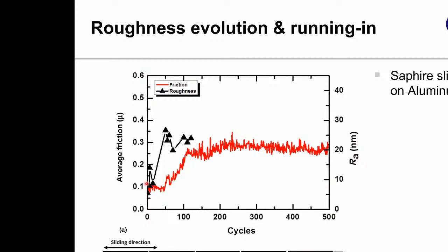Okay. So what this plot shows is experimental work, sapphire sliding on aluminum by Pancho Stoyanov, working with Martin Dienwiebel and Richard Kromick. The y-axis shows the friction coefficient, and the black curve shows the surface roughness measured in situ during this experiment. What you see in this case is some sort of running in, a bit untypical since the friction coefficient actually goes up, but at the same time the surface roughness goes up. There are not many experimental results of this nature in the literature, but some indicate that surfaces don't just flatten during sliding, they can also roughen, and there seems to be some steady state surface roughness that develops during frictional loading and during wear.